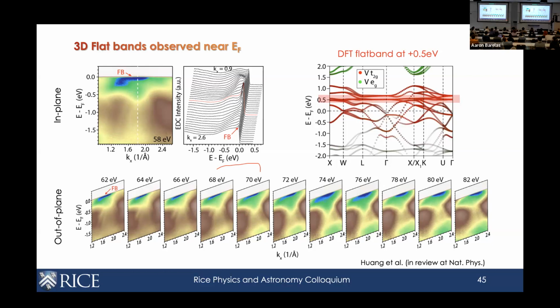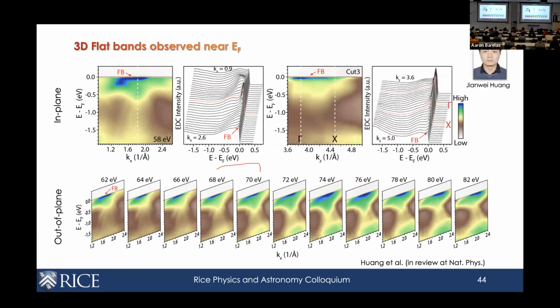That we don't know. It could be that, or because the tight binding I showed you is without spin-orbit coupling. When you add spin-orbit coupling, the two become degenerate at other points. But experimentally, this one is very close to the flat band at the Fermi level, and we can only resolve one. So the answer is we don't know.